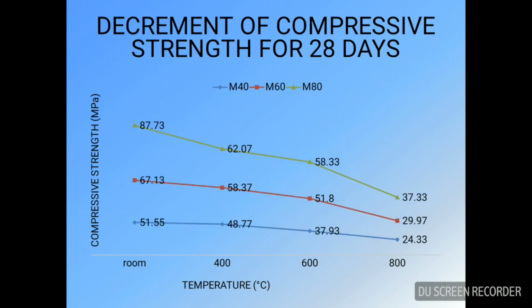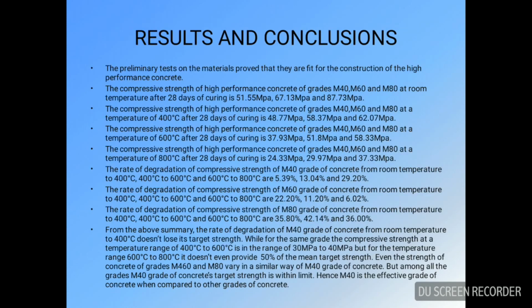Then for the decrement of compressive strength after 28 days, M40 and M60 had only a small inclined curve, but M80 had a major downward curve. This was because of the microsilica content added in the concrete cubes, while the amount of microsilica in M40 was 0. For M60 it was very minute, so the water content was also increased, because of which the cracks were late to occur. Now for our results and conclusions.